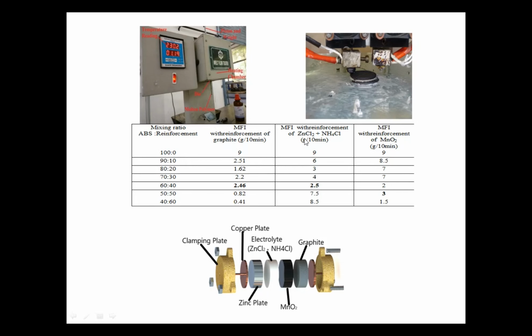Now, a similar study was performed with zinc chloride and ammonium chloride, and you can see there was a different observation. For 70-30, the graphite MFI was in the range of 2.2, whereas for zinc chloride and ammonium chloride it was 4. And once a similar study was done for MnO2, it was 7. That means a particular composition of reinforcement of zinc chloride, ammonium chloride, MnO2, graphite into the ABS cannot give me a particular range of MFI, right?